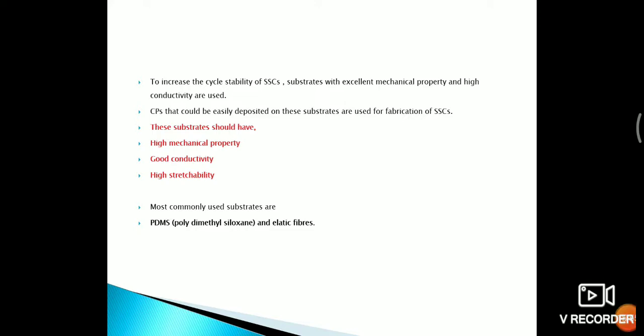To increase the cycle stability of stretchable supercapacitors, we have two methods. First one is addition of substrates of excellent mechanical property and high conductivity, and second is using combinations of conducting polymers with other metal oxides or carbon materials. First, we can discuss the addition of substrates with the conducting polymers. The conducting polymers that could be easily deposited on this substrate are used for the fabrication of stretchable supercapacitors. And these substrates should have high mechanical property, good conductivity, and high stretchability. The most commonly used substrates are polydimethylsiloxane and elastic fibers.